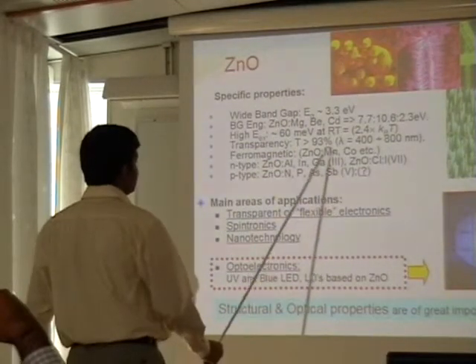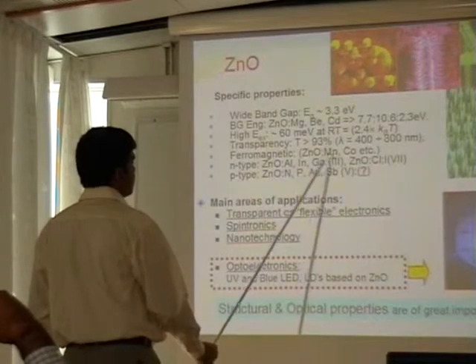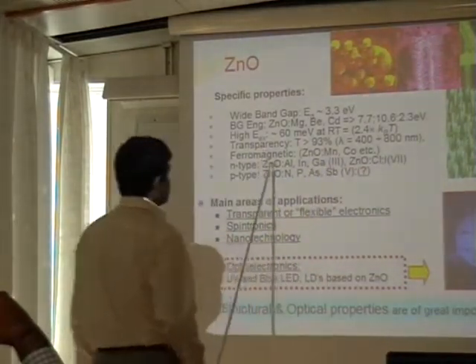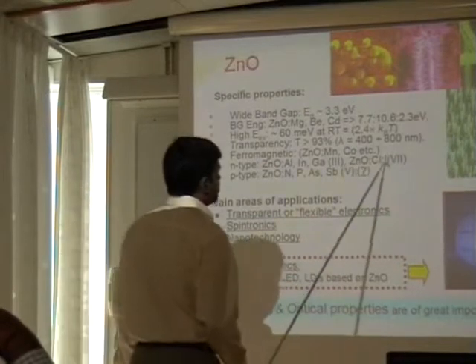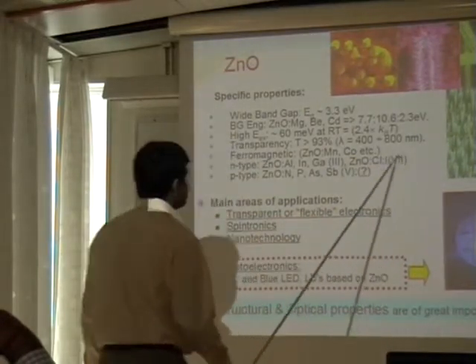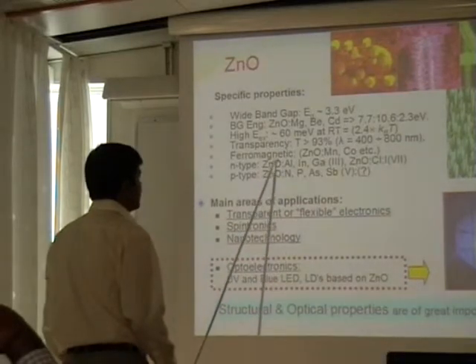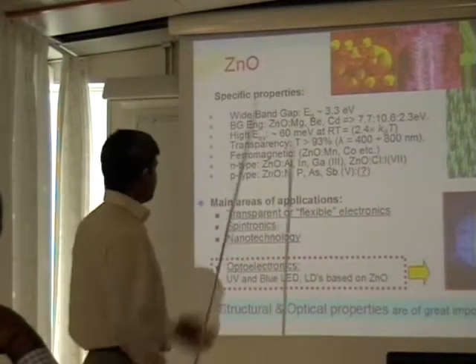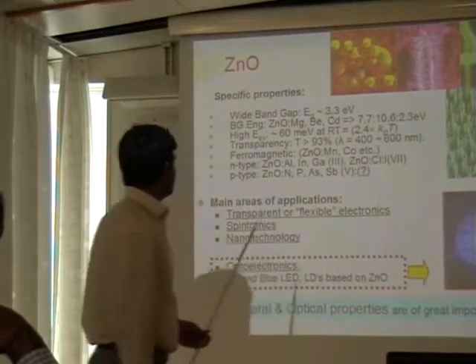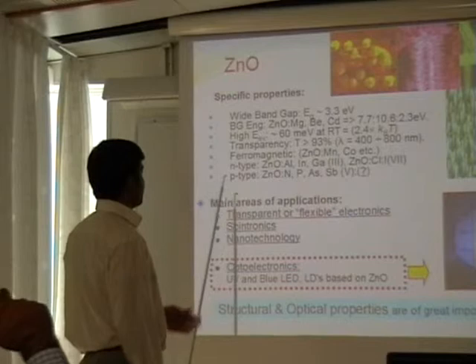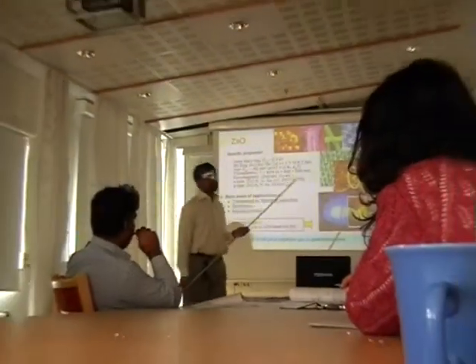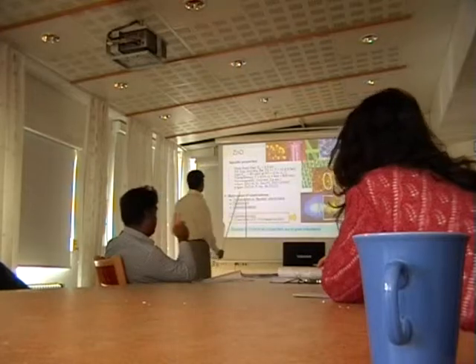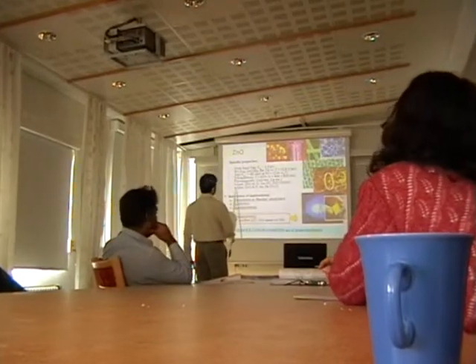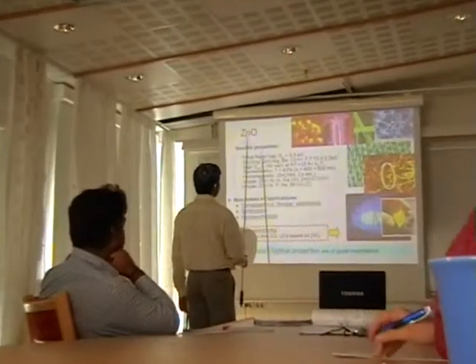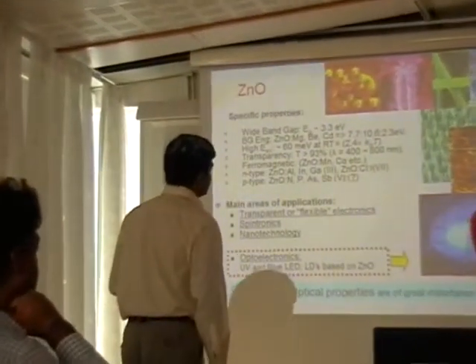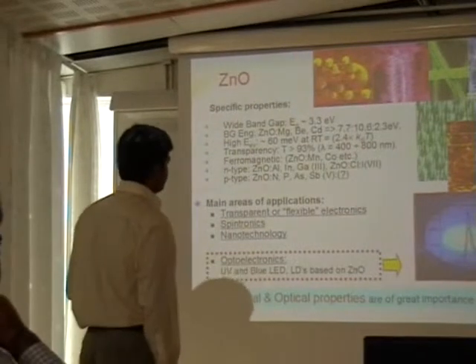For group 3 elements, gallium, indium, aluminum, they substitute at the zinc place, while chlorine, iodine, group 7, they substitute at the oxygen. But the most important dopant for n-type is hydrogen, because doping with hydrogen shows n-type behavior, since its ionization energy is 13 milli-electron volt.